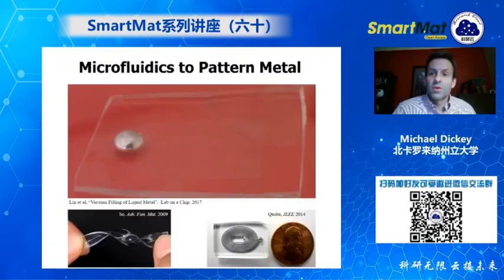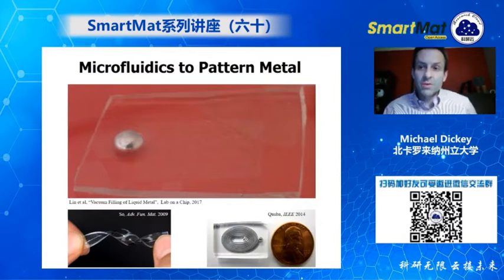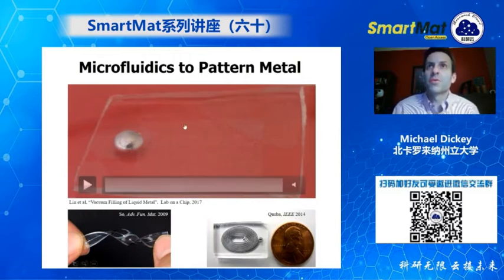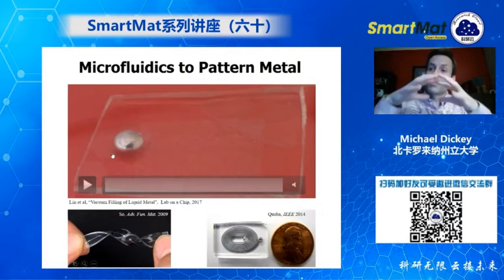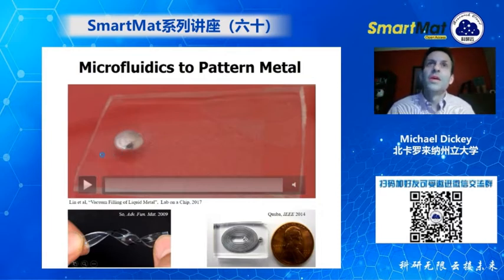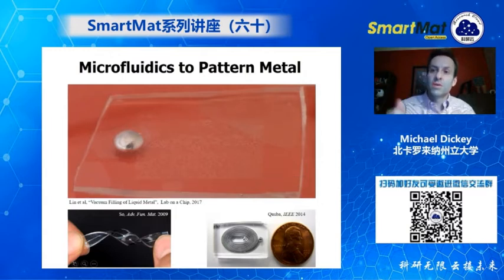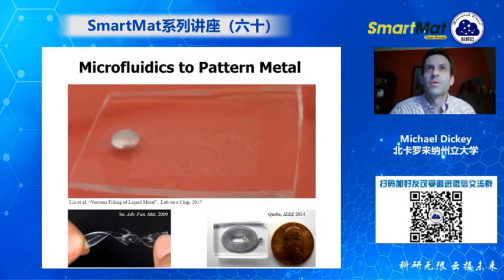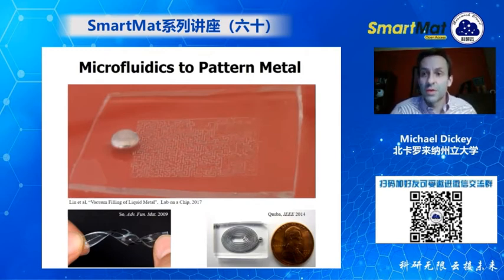So that's one way you can pattern the metal, but there's other ways, including injecting it. So these are very unique things. Usually you cannot do this with metals. So in this video, there's some microfluidic channels, which you can sort of see here. And there's a droplet of liquid metal placed over the inlet. It's a little hole. And you can see the student's reflection here. The student has put it inside of a vacuum chamber, which has pulled all of the air out. Now, if you watch, you'll see the student is going to come and turn the valve, which will let air back into this chamber, and it will push the metal into the microfluidic channel. So it's a very simple, hands-free method of patterning the metal.